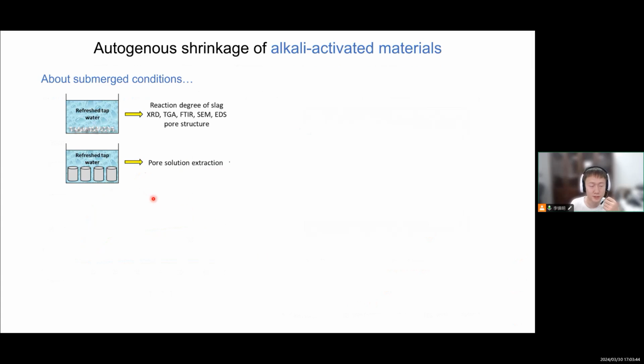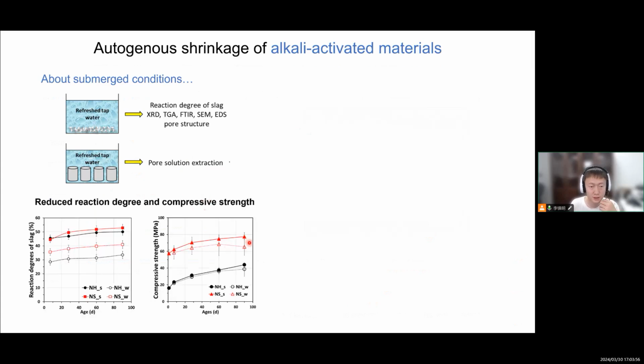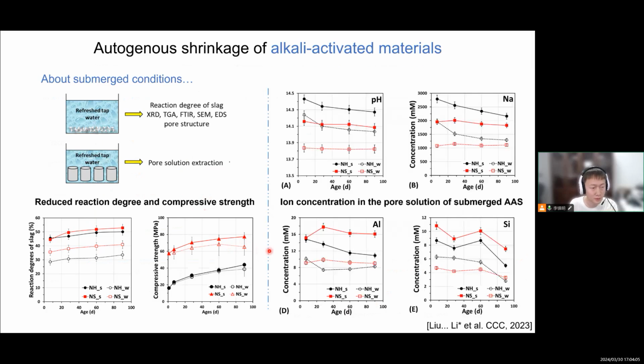For example, as we found by experiments, and this work is mainly done by a PhD called Liu Chen, the only PhD I'm supervising now, the compressive strength will be lower if we put the alkali-activated slag samples into the submerged condition. The reason is leaching of the ions from the pore solution to the environment. So the pH of the pore solution will reduce, and the same happens for all the other elements, sodium, aluminum, silicon, which are key elements to form the reaction products. When the samples are in contact with water, these ions tend to leach out from the matrix, which will of course influence the reaction rate, reaction degree, and even induce the decomposition of the gel, which is really not good. We didn't show the flexural strength here, but actually I can say that it is even worse.